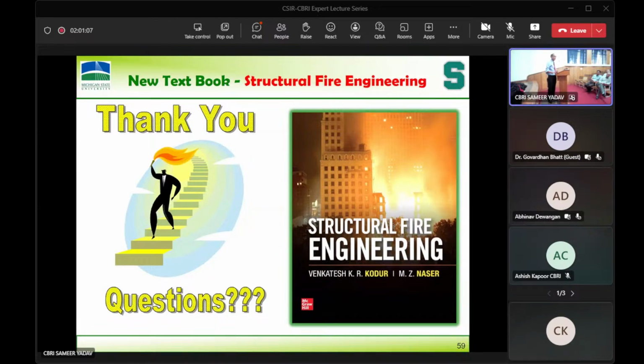There are guidelines for that. So you use a 10% reduction. Let's say the rebar is 400 megapascals. If it goes to, let's say, 550 degrees centigrade and then cools down: in the heating phase itself at 550, the rebar has lost 50%, so it will have only 200. But if it completely recovers, then it will have 10% less than the original.